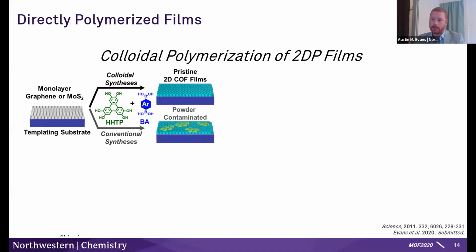But in those cases, something that was fundamentally limiting for us was that the films we made were contaminated by powders that precipitated simultaneously in the synthesis. So for example, if you have a small amount of powder and it creates a pinhole defect and then you try to deposit an electronic contact, well, you're going to get shorting. And those sorts of things made it really challenging to reliably build devices using that type of approach.